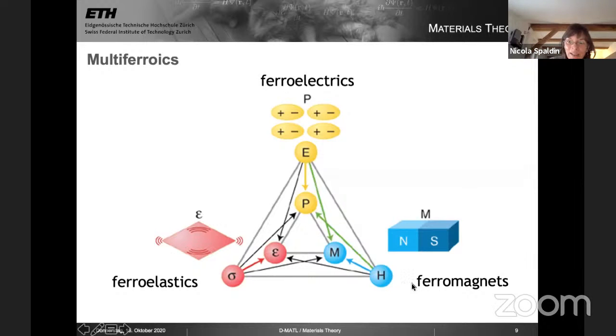For example, in a ferroelectric ferroelastic, the application of an electric field will deform the material. And this, of course, we're familiar with as the piezoelectric effect. In a ferroelastic ferromagnet, when it's strained, it'll change the magnetic properties. And this is used, for example, in magnetomechanical actuators or in piezomagnetism. For the ferromagnetic ferroelectrics, one can, with a magnetic field, modify the electric polarization, and with an electric field, modify the magnetization. This is what's called magnetoelectric coupling.